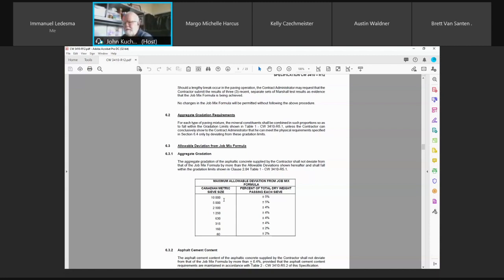So you did a sieve using the Canadian metric sieves, saving everything on the 5 millimeter and above. Now you've got to take it and screen it over a 4.75. You're handling it twice. They don't recognize that. Because if you read the other tests required for asphalt, they fall under ASTM. I've mentioned to the independent labs to tell the city to smarten up.